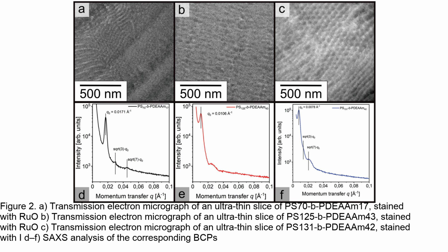The block copolymers are dissolved in chloroform and the resulting films are annealed at 130 degrees Celsius to induce microphase separation. Transmission electron microscopy (TEM) and small-angle X-ray scattering (SAXS) are used to analyze the morphology. For the block copolymers PS70-b-PDEAAm17 and PS131-b-PDEAAm42, a hexagonal cylindrical morphology is observed, with the PDEAAm block forming cylinders in a PS matrix.